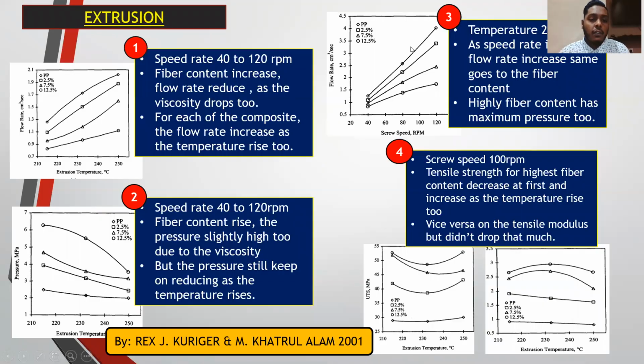And for the literature review on extrusion parameters, we can see when the temperature is high, the flow rate is also high, and the viscosity drops. This means it has a proper mixture of the composition. And when the temperature is high, the pressure is also low, and this will produce a good composite. And when the speed of the screw increases, the flow rate also increases. This means the pressure is a bit low.